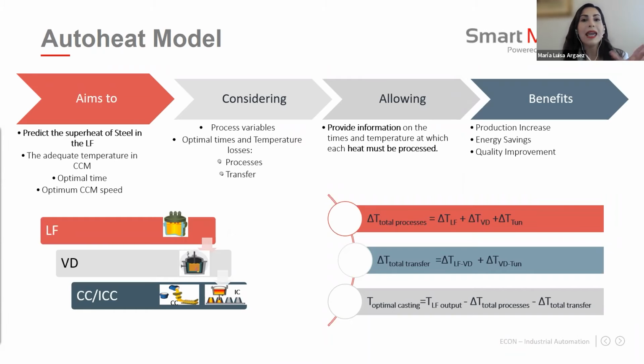Well, the auto-heat model aims to predict the superheat value that must be given to the steel in the ladle furnace, allowing to achieve an adequate temperature in the CCM, to have an optimum time and an optimum CCM speed by obtaining the correct superheat value. And here we consider several process features such as steel grade, heat weight, additives in each process, times, and the transfer times. And this allows us to provide information of the times and temperature at which each heat must be processed. Also, with the benefits of production increase, energy savings, and quality improvement.